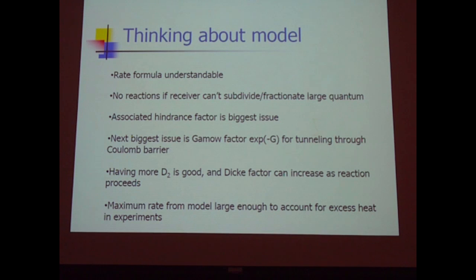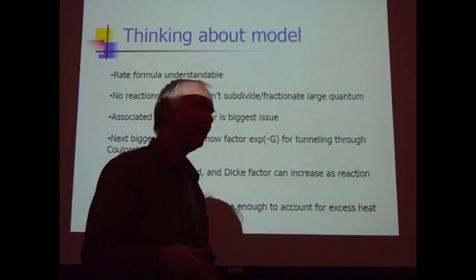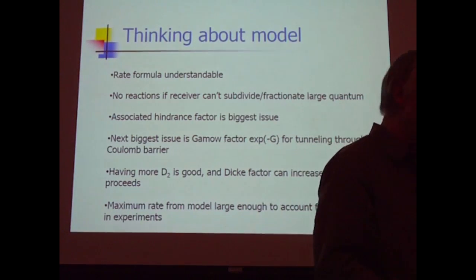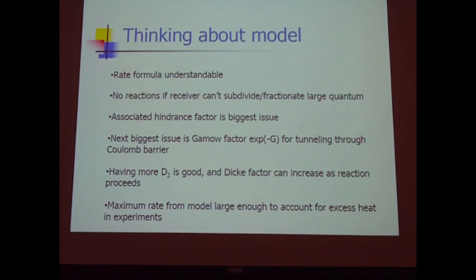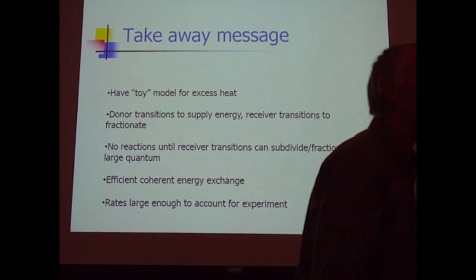It turns out in the model the ability of the receiver to fractionate quantum is exponential in terms of the number of receiver nuclei you have. So if you put in magnetization, you can get nuclear spin polarization. You have the possibility of increasing the rates. So if you're at a low hindrance factor and you double the number of nuclei participating, you're going to get a gigantic increase in the ability of the system to fractionate, and you're going to see a large impact from a magnetic field. And by the way, the selection rules, like I say, seem to be consistent with the experimental observations.